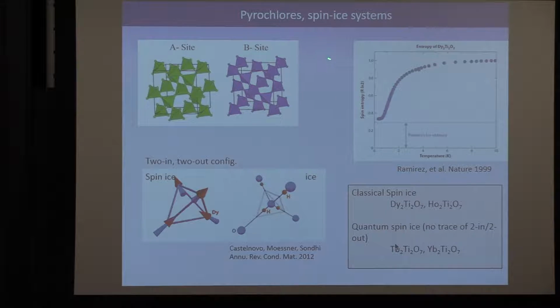Okay. So what is the spin ice system, right? So here you have in each tetrahedron, the spins can either be in or out, and that reminds you of the water ice problem, right? In water ice, the hydrogen has two positions to sit, and this gives rise to extensive entropy at very low temperatures. So in the spin ice problem, Ramirez first showed that indeed the entropy at very low temperatures is extensive. It's huge. It scales like a volume. And in fact, it's in rather good agreement with Pauling's formula.